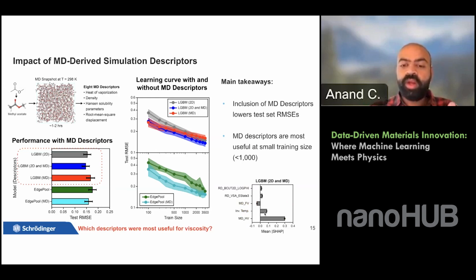And we provided the inverse of temperature as a descriptor because the inverse of temperature has a more direct linear relationship with viscosity as opposed to the temperature. And we see that, as you expect, as you increase the temperature, the viscosity goes down. And so using a combination of 2D descriptors or graph convolution approaches plus MD descriptors seems to be the best way to go forward in obtaining accurate machine learning models, especially at low data set sizes.